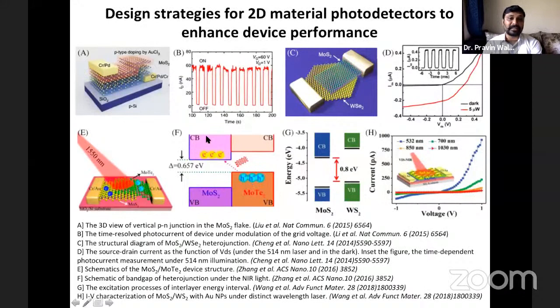And you can find that the conduction band of MoS2 and the valence band of MoTe2, the highest conduction band of this and valence band of this, you will find the energy gap is just 0.6 electron volt, right? And therefore it can operate in the NIR region, right? So a 1550 nanometer wavelength range. So this device can work at a wide spectrum as compared to these two devices, right?